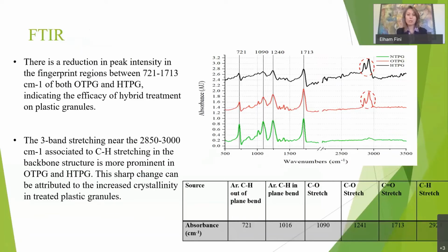So just some of the science behind it and the characterization we have done. Here you can see the green is just the neat plastic, ground, with no treatment on it. And then the red is when we actually use the oil treatment on the surface. We basically use biografting to have certain biomolecules of the oil attached to the surface of the plastic. And then the hybrid, which is HTPG here, is the one that has carbon coating on top of that. If you look here in the region of 721 to 1713, you can see that the peak intensity here is reducing. There is a reduction in that region from this to this after treatment.